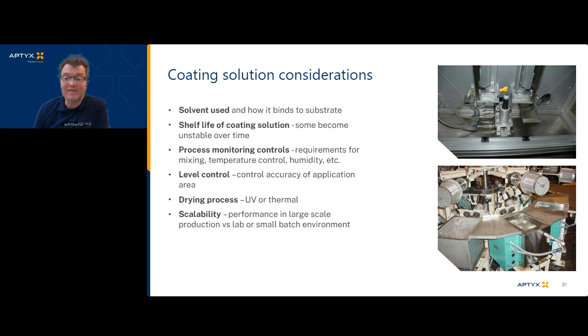Still a very long process, because they wanted to make sure that the residual solvents that were being used were fully removed. And that was accomplished by thermal drying and using vacuum ovens in various steps of the process. We couldn't use the vacuum ovens in the initial steps because we would devolatilize the solvents too quickly, causing some surface anomalies on the coating. So we had to thermally dry the process first for a short period of time, then apply a vacuum.